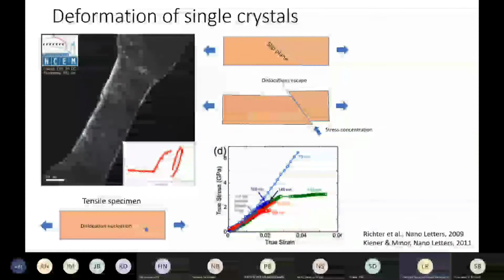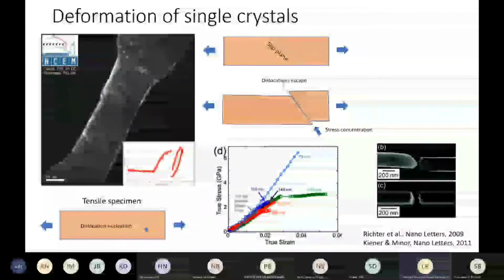For a 75 nanometer sized material, the ductility is very poor. You don't really see plasticity occur in this because dislocations escape. And this is also seen for different kinds of films. You will see some kind of brittle failure and other kinds of features.